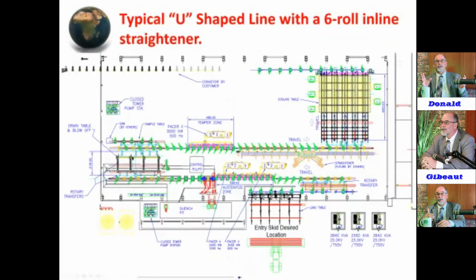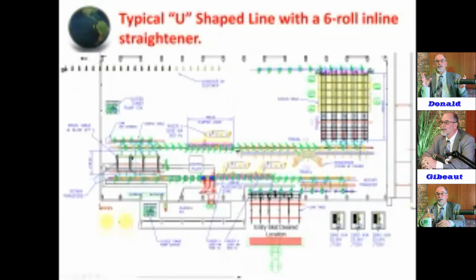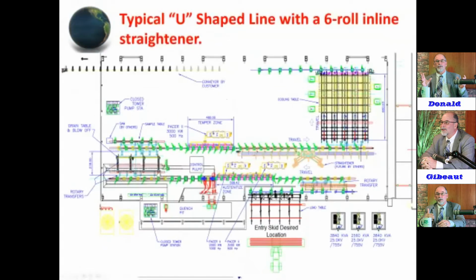Now here's another line, a U-shaped line. You can see the forklift here bringing the pipes in on an inclined table. It's brought into the system through the austenitize, goes through the quench system here, through the transfer table. Here's the sample position in this system. Then it goes through the temper. But then here we have a 6-roll straightener. A lot of our lines on the lower tonnage don't require a straightener, but we encourage customers to build in the conveyor section so that at any point that you need it, you can add it for just the cost of the straightener, basically. If you don't have the conveyor sections in here to allow this adaptation, there's quite a cost, and you don't know if you can fit it in your building.